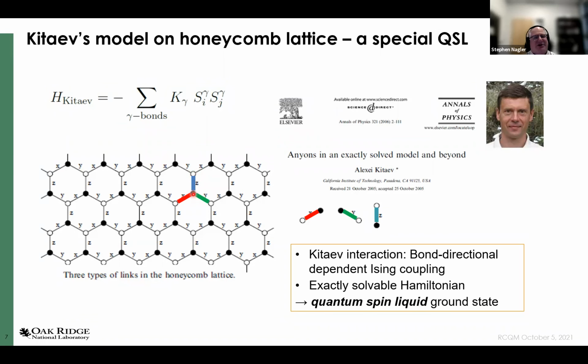The reason I have a black and white dot here for the spins is it's actually a bipartite lattice, right? And I assume that I have an Ising type interaction, in other words, a uniaxial interaction with each of the nearest neighbors, but the uniaxial axis actually goes parallel to the bond. So that gives me 3 different Ising interactions along mutually incompatible bonds. And for spin 1/2, this model can be solved exactly.